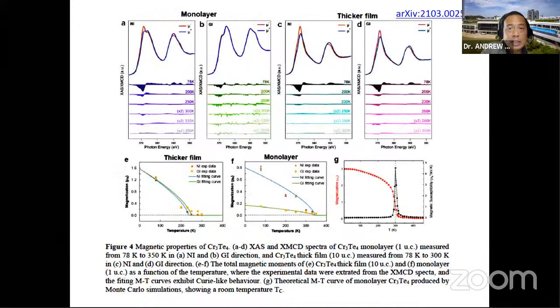And the more important thing is the magnetic measurements show that for the monolayer, here comparing the monolayer and the thicker film using XMCD again, you can see in the monolayer film up to around just above room temperature, there's still some dichroic signal, whereas the thicker films, it disappears below room temperature. So we plot the Curie temperature. You can see that for the thicker film, the transition occurs about 200 and something Kelvin. And for monolayer, transition is above room temperature.